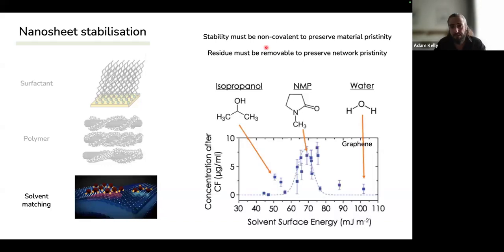So we take things like solvents. This is the surface energy of a solvent versus the concentration after we apply these techniques. This is for graphene. And what we find is that certain solvents give us much more exfoliated material compared to others. So when you take graphite and you just apply liquid phase exfoliation techniques, if you do it in water, we don't really get any material at all because water is a bad solvent for exfoliating in. We find something like NMP or a bunch of different solvents in here like CHP, and they're quite good. So what you want to do is choose one solvent and then use it to exfoliate your material. So then at the end, once you've printed it, you can remove the solvent and all you're left with following printing is your active material.